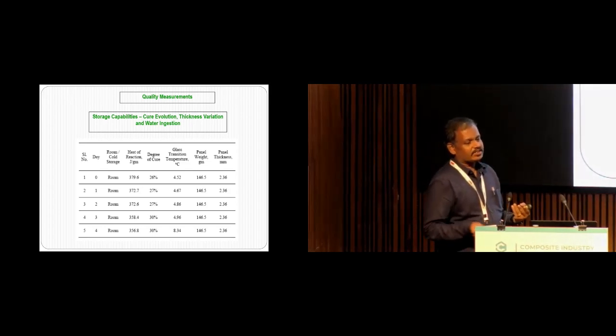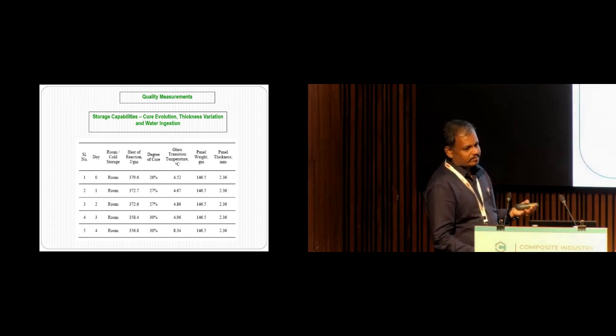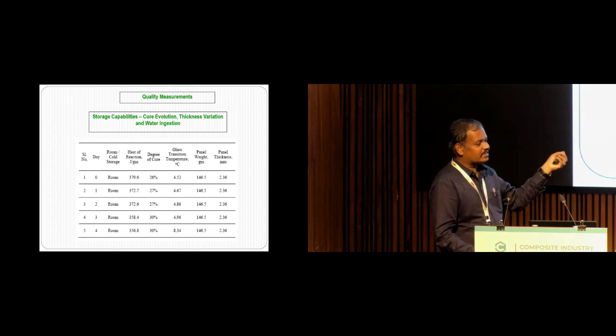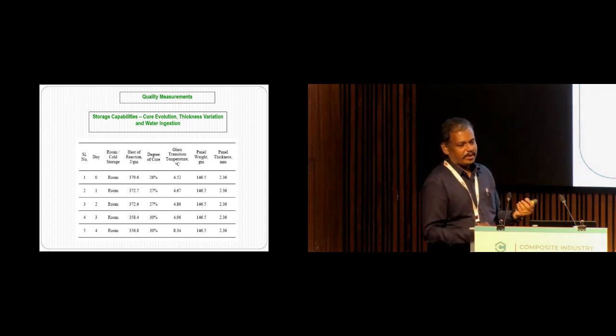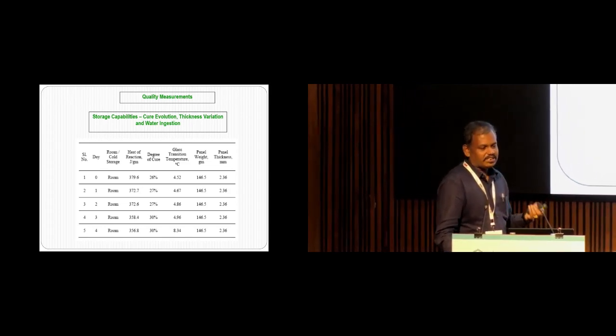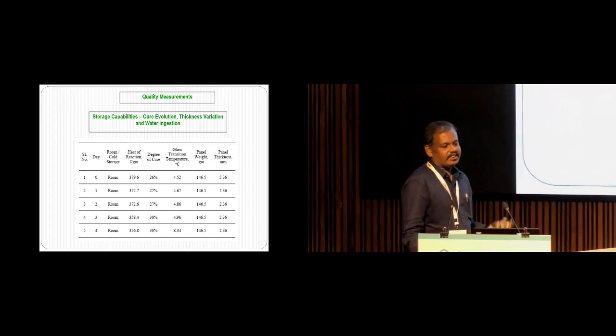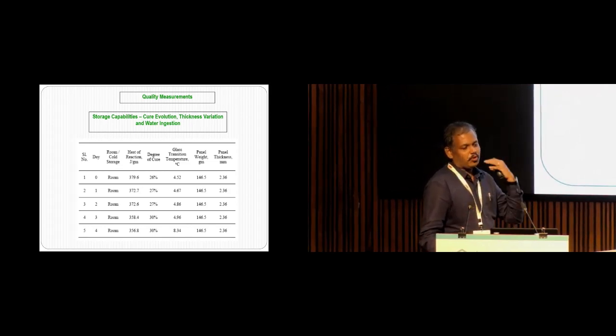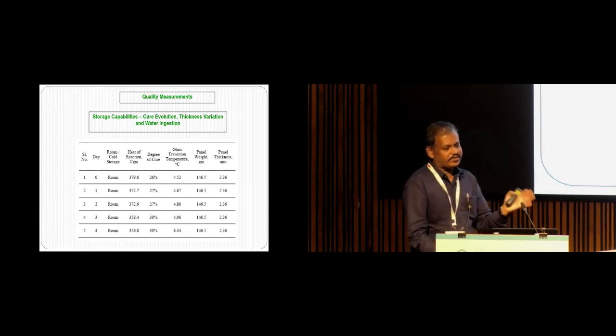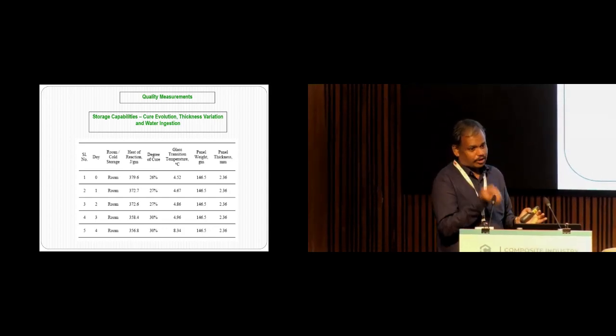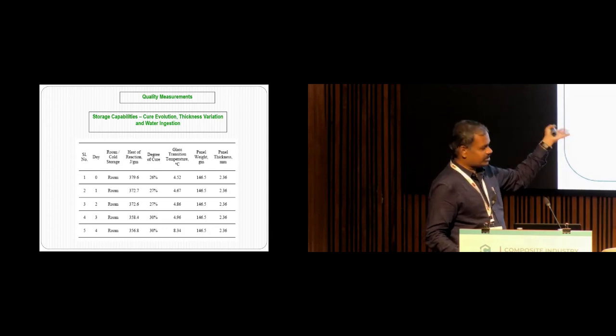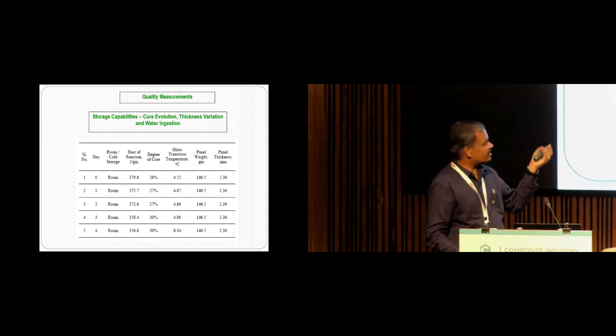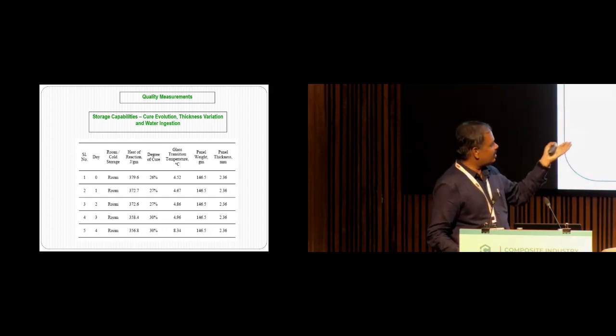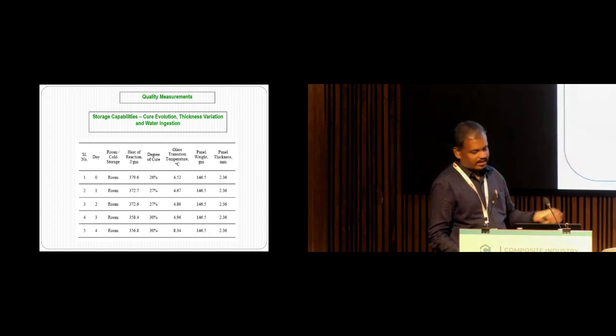We can say there is always a thermal stress induced within the composite panel, which may add to a rise in the degree of cure. Generally, because RTM6 resin is a thermally activated resin, you don't need any curing aids, no initiator or accelerator, to cure it. If you apply a temperature of more than 180 degrees centigrade, it will automatically start curing. You cannot stop it, but you can reduce the rate of curing by reducing the temperature. At every temperature, once it is thermally activated, some degree of curing will be happening. So there may be some residual heat in the panel at room temperature, which would be the reason for the slight increase in the degree of cure.